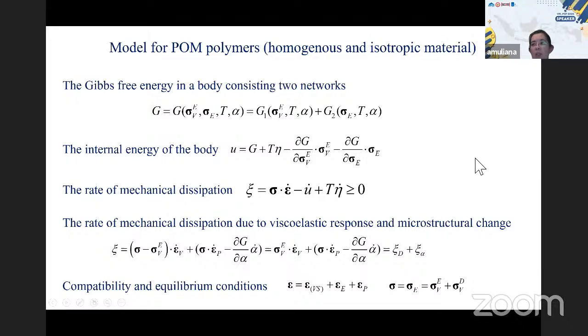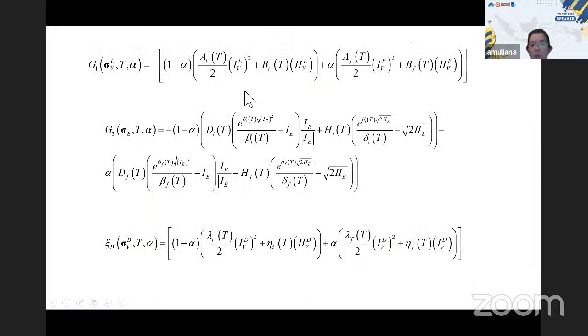The key point in deriving the model is picking the Gibbs potential. How we pick this, of course, is based on the experimental data available to us, right? Here we assume an isotropic and homogeneous material. Just to show you an example, inside this Gibbs potential we have material parameters. We call them A_i and B_i, which are temperature dependent. These are our material parameters. You can think of this as a compliance, or associated with the modulus of the material.